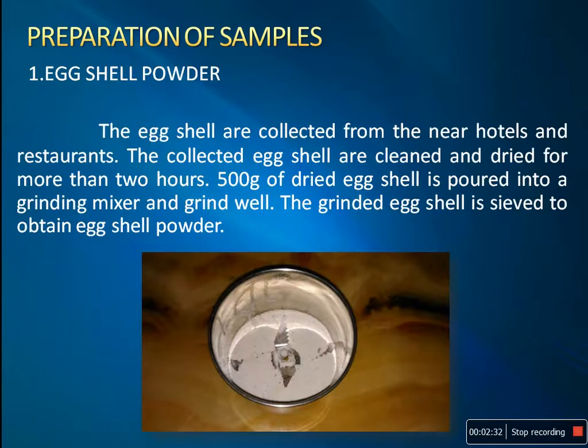The actual preparation of samples: the eggshells are collected from nearby hotels and restaurants. The collected eggshells are cleaned and dried for more than 2 hours. The 500 grams of dried eggshell is poured into the grinding mixer and ground well. The ground eggshell is sieved to obtain the eggshell powder.